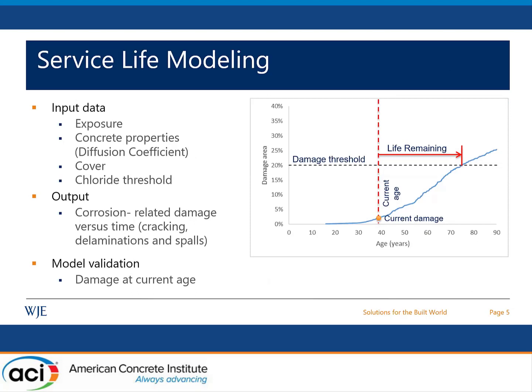So as I mentioned, the inputs are derived from the condition assessment findings that we measure directly from the existing structure. And these input data include exposure and concrete properties parameters. And we collect this information based on testing of the concrete cores and the chloride profiles.